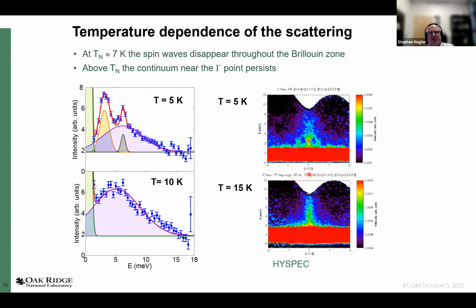And here's the similar plot to what I showed before, intensity versus energy. This is measured in a slightly different way. But you see these are the sharp peaks, and here's the continuum part. If I raise the temperature above 7 Kelvin, the sharp peaks go away and I'm left with the continuum.